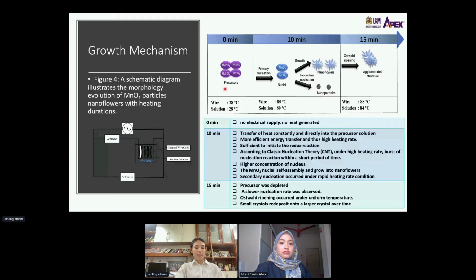After switching on for 10 minutes, the temperature of the wire reached 85 degrees Celsius, while the precursor solution reached around 80 degrees Celsius. This observation suggests that the heat transfers rapidly into the precursor solution through the localized heating method. This is explainable because the localized heating method allows the heat to transfer directly and constantly into the precursor solution. So this offers more efficient energy transfer and thus a high heating rate. This temperature is sufficient to initiate the redox reaction between potassium permanganate and manganese sulfate.